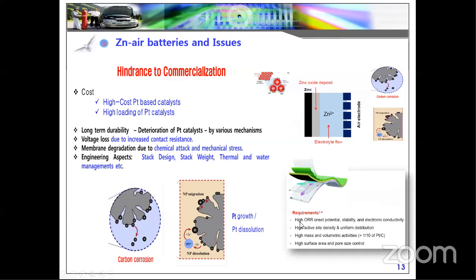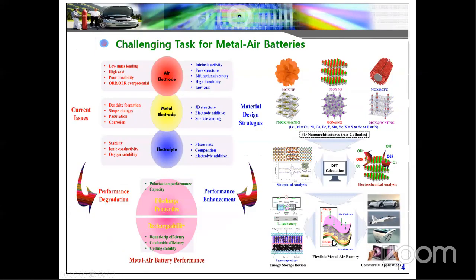That material should have a high ORR onset potential, high active density, uniform distribution of the active catalyst, and high volumetric activities, and surface area and pore size are among the important factors. This is a challenging task for metal-air batteries. When we fabricate metal-air batteries, we need to consider 3 different available ingredients: air cathodes, metal electrodes, especially zinc, meaning for a zinc-air battery a zinc-based electrode, and electrolytes. So these are the current issues.